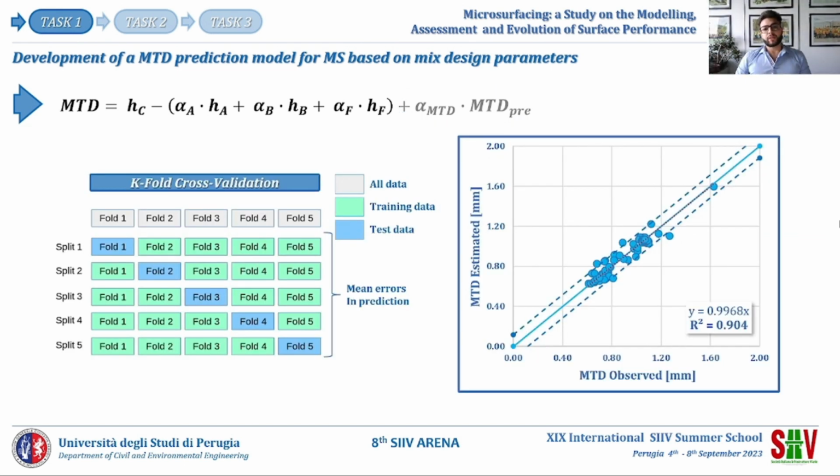Statistical performance of the model was recorded by using a k-fold cross-validation technique to confirm the good generalization and the basic assumption behind the modeling phase. The model was applied then to the whole dataset, and the accuracy was assessed by means of statistical metrics. Given the heterogeneity of data collected, the model shows excellent prediction performance with an R-squared of 0.9.